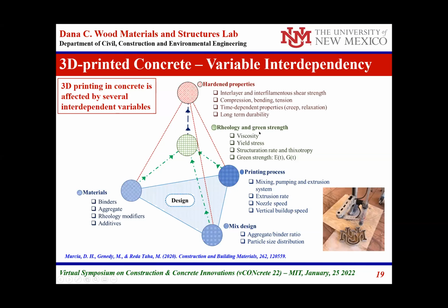Rheology is basically the ability to place this material into the layers required and in the geometry required. That's controlled by the viscosity, the yield strength, the structuration rate, the ability to build up, and the thixotropy. Then the green strength, represented by the modulus of elasticity and the shear modulus of the green concrete that is still in the fresh state.